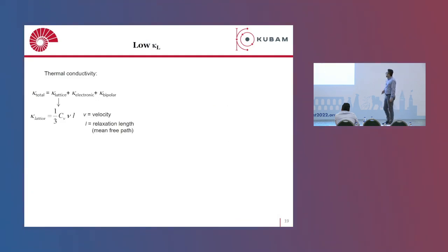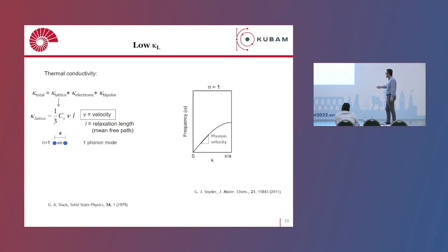So for the lattice part, we can also tune the velocity because the lattice thermal conductivity depends on the phonon velocity as well. Here is a simple scheme showing that if you have a small unit cell composed of exactly the same atoms, you have only one phonon mode here, the longitudinal phonon mode, and the slope of this dispersion curve is giving you the phonon velocity.